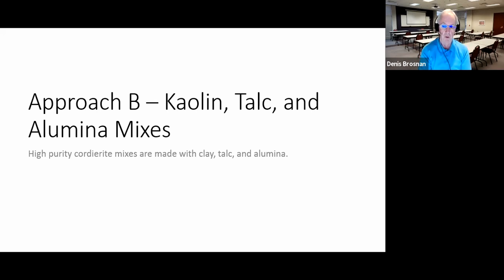The more interesting way is to make high purity cordierite. Then you use kaolin, aluminum silicate, and talc, magnesium silicate. And as I've said before, you have to sweeten it up with a little bit of alumina to hit your compositional goals. So this is the way that we make high purity cordierite.